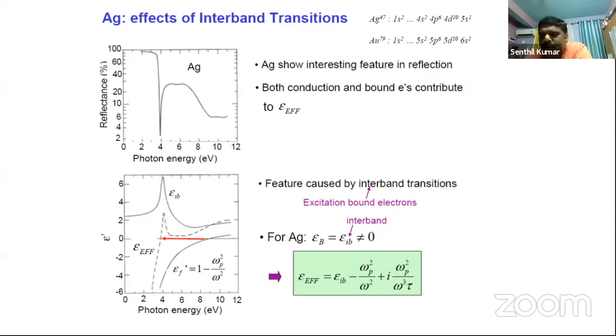Even though according to the configuration 5s is the valence electron, energy-wise it can hybridize with the 4d orbital. So the sd hybridization always takes place, same as in the case of gold, which has a 5d10 6s1 electronic configuration. The 6s and 5d orbitals can always hybridize; the d electron can go to the 6s orbital and the 6s electron can come back. So the hybridization effect is always there, and that's why the bound electron contribution is appreciable in cases like gold, silver or copper.